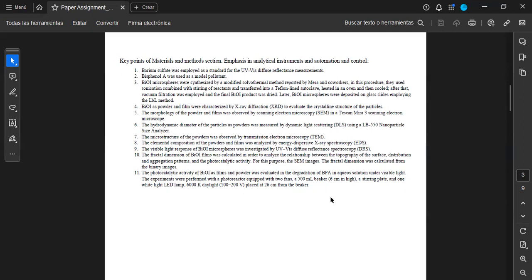After that, we had that the fractal dimension of the BiOI films was calculated in order to analyze the relationship between the topography of the surface, the distribution, and also the aggregation patterns, and with this study, the photocatalytic activity. So, for this purpose, the same images were studied, and also the fractal dimension was calculated from the binary images. So they transformed the same images into binary images in order to do this study.